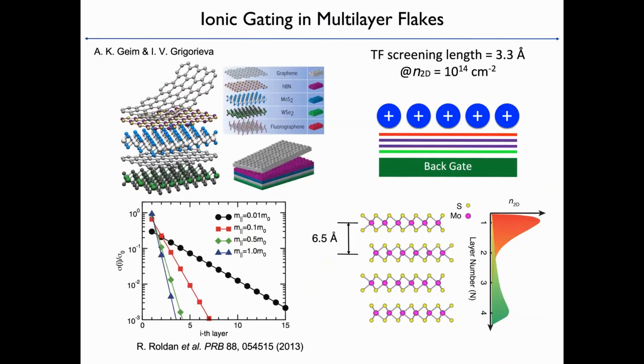So this is a technique very, very similar to the transistor, but some special points can be useful to further explore the superconducting state and some spin-related phenomena in the system. One point is, if you consider the carrier density on the scale of 10^14, and the Thomas-Fermi screening length to be very, very short, this means the induced carriers are indeed very close to the one layer, so that if you gate, you can actually isolate a one-layer electronic structure out from the bulk.